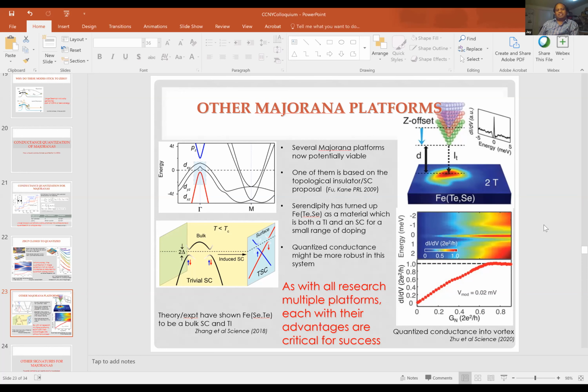No. So what happens is this. Even in type 1, it doesn't matter. Even in aluminum, you'll get pair breaking if you have a thin film. So the only way to avoid pair breaking is to have what's called a low density superconductor. So Fermi energy and delta have to be comparable. So these iron selenide, iron superconductors, for some strange reason, are close to what would be called in cold atoms the BCS-BEC crossover. So they're actually almost like a Bose condensate of Cooper pairs. So when that happens, if you have a vortex, then you can't actually break the pair.